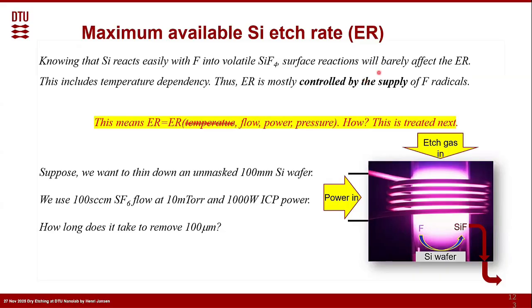So how much gas are we putting in our reactor? How much power? So how do we crack down this SF6, which is not etching, into the fluor radicals? Also, that one is most probably going to have an effect. And the third one is pressure, because we know that the Paschen curve was telling us where is the highest density of creating the radicals. So these are three which are probably there. Now, how? Let's do it in a very heuristic way.